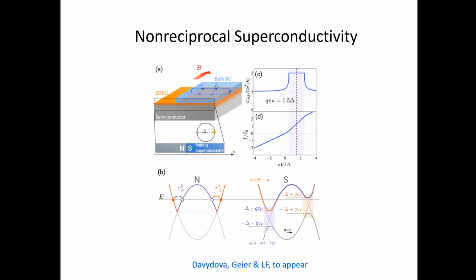Consider electrons incident into the superconductor from the normal region. Depending on the incident momentum, if the momentum of the electron is towards the interface, then the incident electron will be sensitive to the gap on one side of the Fermi surface. On the other hand, if I have a hole going in the opposite direction, which also corresponds to current flowing into the superconductor, then the holes will actually be probing the other part of the gap on the opposite side of the Fermi surface. And when the symmetry is broken in the superconductor, the gap is asymmetric, and this will lead to an asymmetry in the IV characteristic.